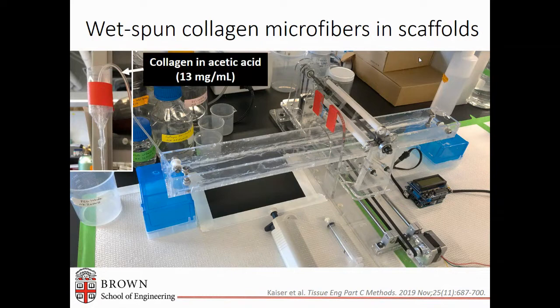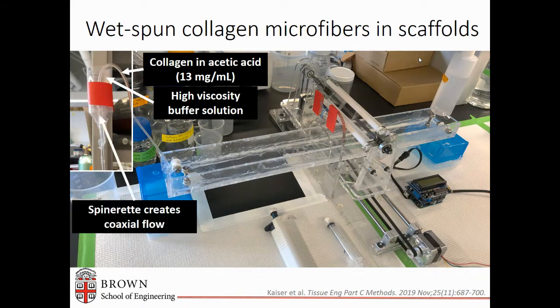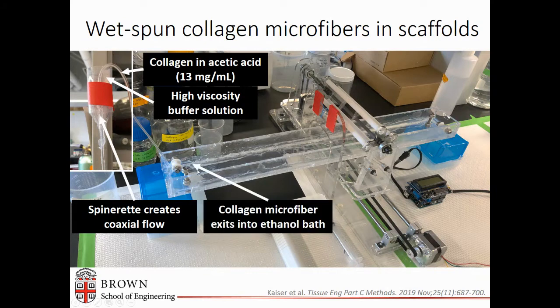And what we do is we have a high concentration of collagen that is fed in through this tube and surrounded by a high viscosity buffer solution so that as it moves through this spinneret, it gets formed into coaxial flow that goes through about a meter of tubing and exits into an ethanol bath to dry.